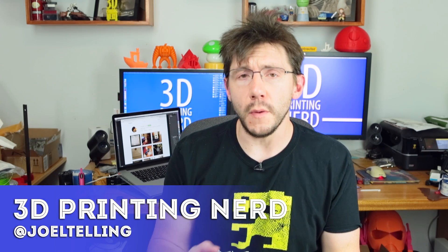So I was talking with Matt over at Printed Solid, and when you add Colorfab's glow in the dark filament to your cart, you're presented with an informational message that tells you it could be damaging to your nozzle and you should probably get a hardened or treated nozzle. I was like, Matt, why is that? I know carbon fiber filaments can cause damage to your nozzle, but glow in the dark filament as well? And he said yes, and here's why. The chemical inside Colorfab and other glow in the dark filaments can actually be as hard and tough as the carbon fiber particles inside carbon fiber filament, meaning it's going to be just as hard on your nozzle and can cause just as much damage.